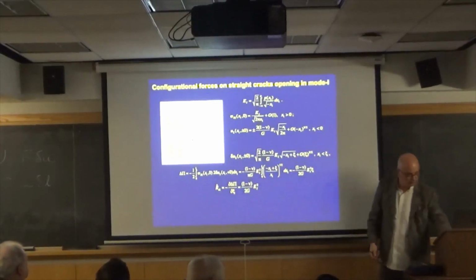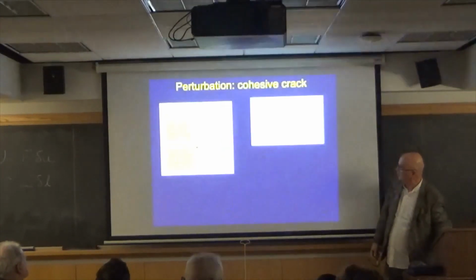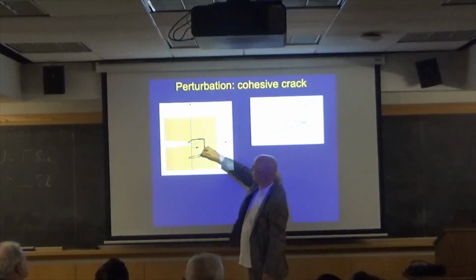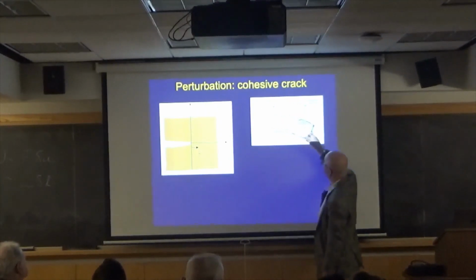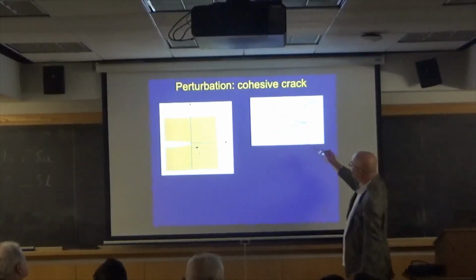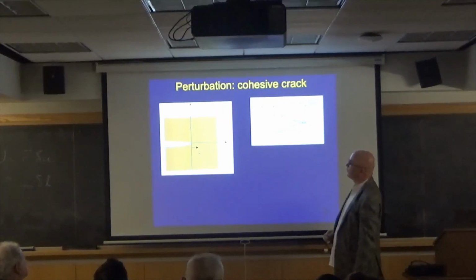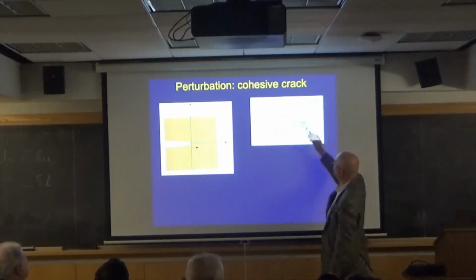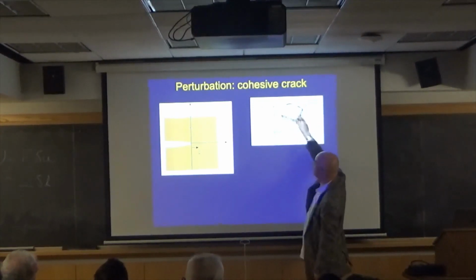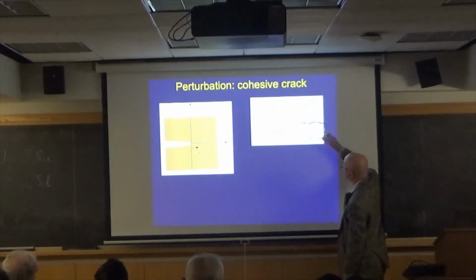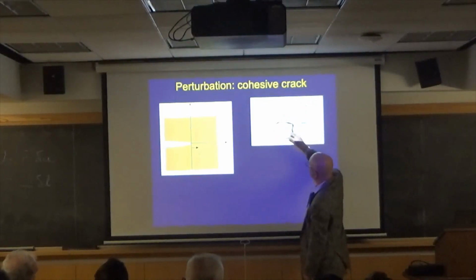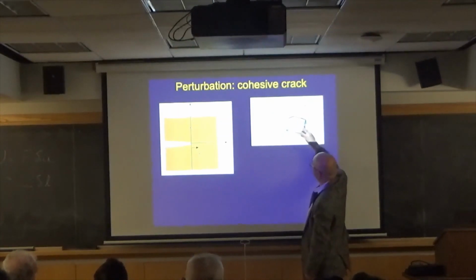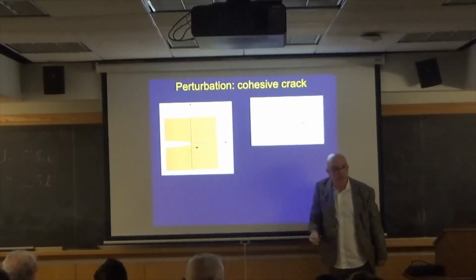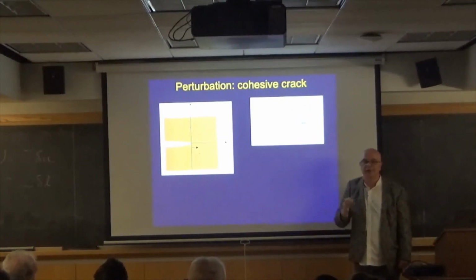So I allow ourselves to allow a process zone, if you will. Like imagine a plug of nonlinear material. It could be microcracking, it could be plasticity, which you can model perhaps as a cohesive zone. Now what I do is I evaluate again the full elasticity solution for a cohesive crack, which is not easy mathematically. I evaluate on this surface some configurational force. I take the small scale yielding limit where this process zone goes back to zero, and it turns out that the force, the x component of the force which is interacting between this and the far field, does not disappear, and it's equal exactly to J integral over the energy release.